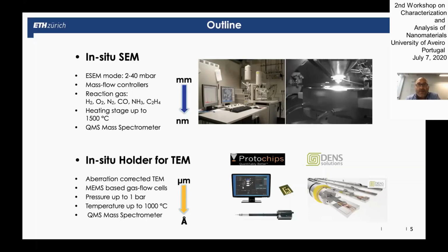And then, yeah, when you have controlled gases, here's a gas feeding system that we built here, for example, in the back. You can then control the atmosphere in the reaction chamber. And yeah, in our case, we also have mounted the mass spectrometer, so we can analyze the composition of the gas phase inside the chamber. And you can heat the sample, and then you can study material in a given atmosphere and look at morphological changes, for example. And the good thing is you can do this in such a microscope in the range of like a millimeter. That's the size of your sample. It's in a millimeter regime. And you can zoom in and then a bit depending on the pressure, you can still achieve resolution down to a few nanometers. So you bridge a quite large scale of lateral resolution.